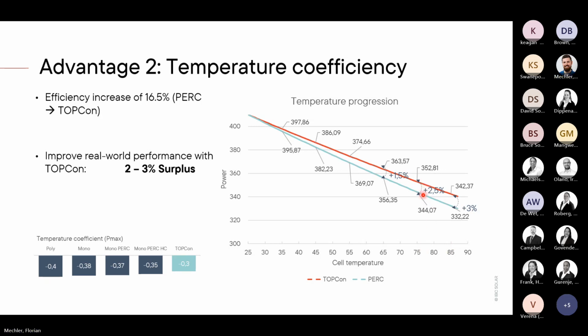So you have here more production of 2.5% at 75, up to 3% at 85 degrees cell temperature. In absolute numbers, it's like 8 watts for one module for these points, and here it's like 10 watts from a TOPCon module to a PERC module. Okay, it's perhaps not that much, but you have not only one module on the roof. Perhaps these are 20 modules or what else on the roof, and with 20 modules, you already have 200 watts as a difference between a TOPCon module and a PERC module. And 200 watts, I think it's really much.